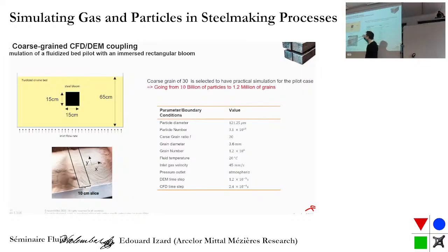So the bloom is immersed in the X like this. We used a periodic boundary condition on the X-axis, only simulating 10 centimeters. Why 10 centimeters? Because in the literature, it's the largest bubble we can find in a fluidized bed. So we have chosen this parameter.